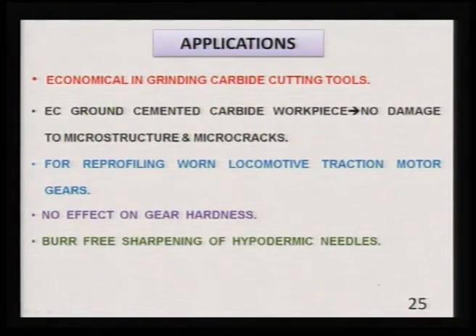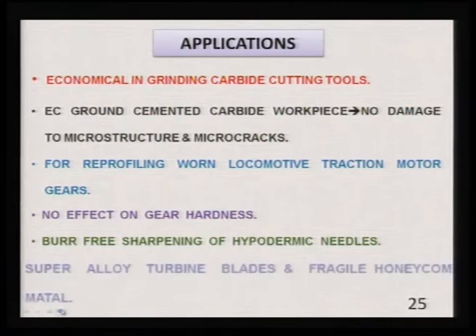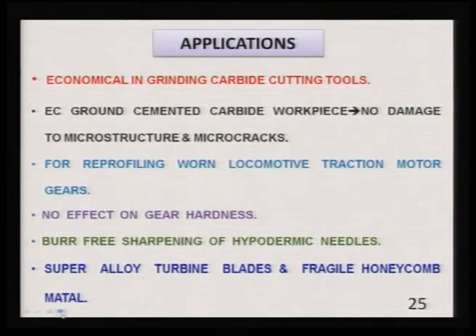You get burr free sharpening of hypodermic needles, which is very important. Even a single burr in this needle will create a lot of pain to the patient. Superalloyed turbine blades and fragile honeycomb metal can be ground by this process. It is also concluded that fine grades and low concentration wheels show a tendency to draw more current and thereby higher material removal rate than coarse grades and higher concentration grinding wheels.